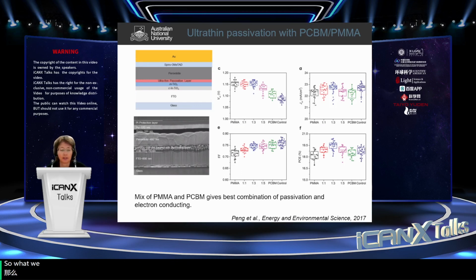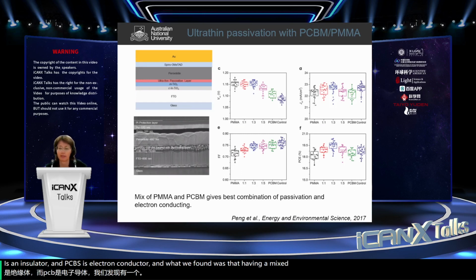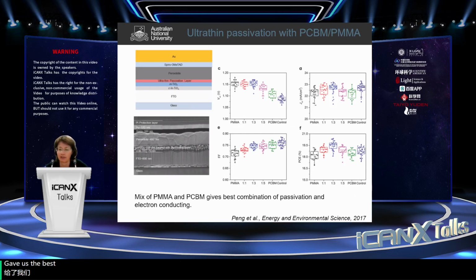So what we used was a mixture of PMMA and PCBM. Now, PMMA is an insulator and PCBM is an electron conductor. What we found was that having a mixture of the two gave us the best combination of passivation and electron conduction. If you just had PMMA, you could get a high voltage, but the fill factor was quite low because it wasn't conducting so well. Whereas if you just had the PCBM, your fill factor was high, but then your voltage was low. By having the combination, we could improve the trade-off and lead to a higher efficiency overall.